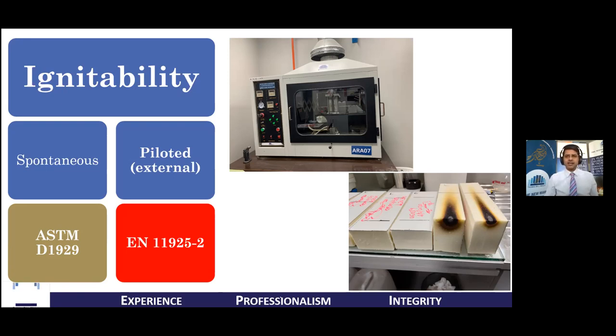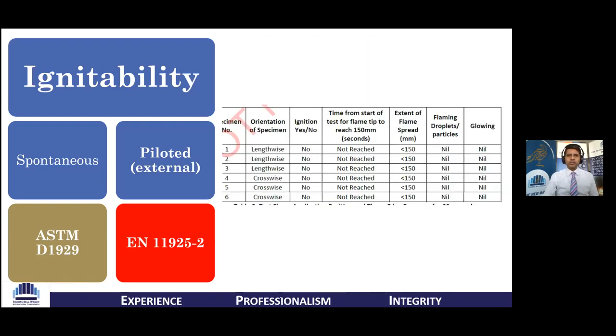So what this does is that it measures the spread of flame on a sample across its vertical surface. And we impinge the edge or the surface with an application of a match-sized flame for a duration of between 15 to 30 seconds. And then what is also noticed is whether this limit of 150 millimeters, as a line, gets crossed by the flame, depending on the rate at which the material catches fire or ignites itself.